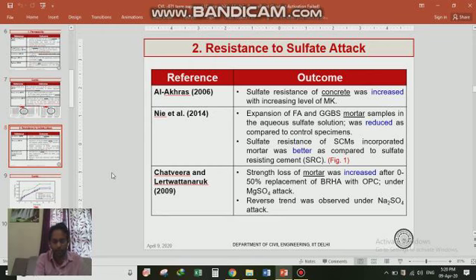Similarly, in 2009, Chatveera and Lertwattanaruk studied the strength loss of mortar, and they concluded that strength loss increased with 0 to 50% replacement of black rice husk ash with OPC under MgSO4 attack. But the reverse trend was observed under sodium sulfate attack.